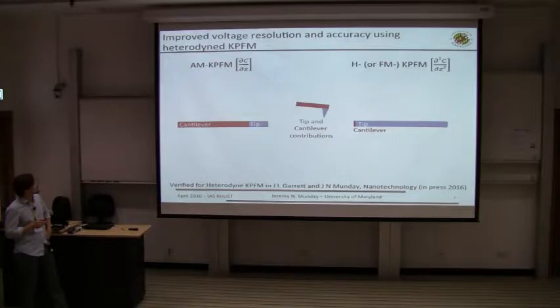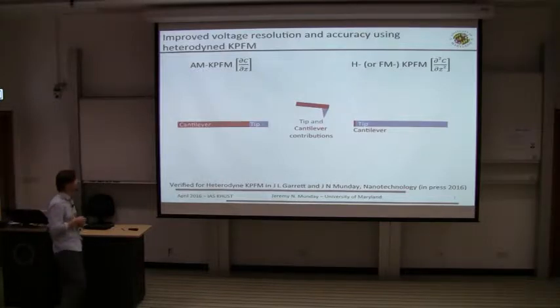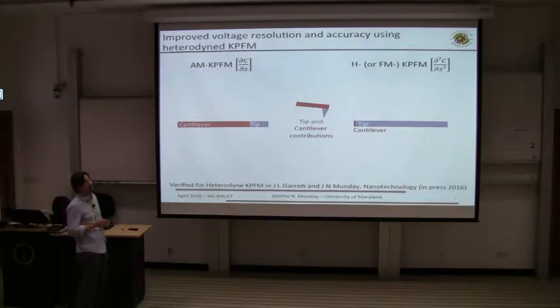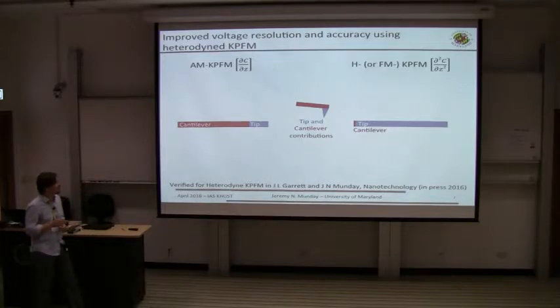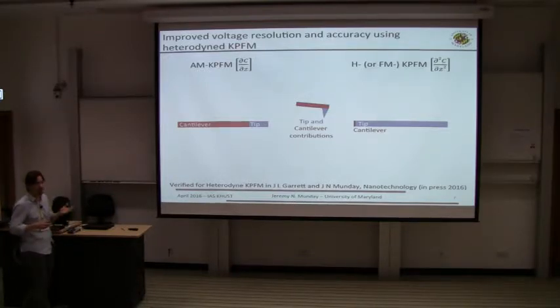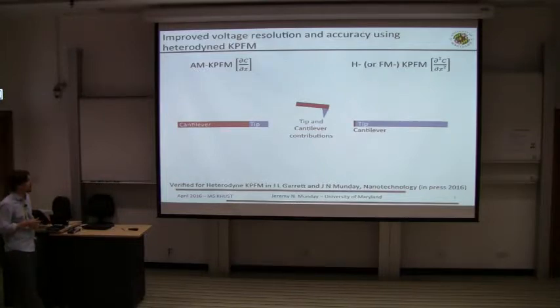Now, with the amplitude modulated, because it goes with the derivative of the capacitance, the first power, you end up getting more contribution from the cantilever than you do the tip, because you've got this very large cantilever here and a relatively small, narrow tip. So if you have something that varies more quickly with distance, then the closest interaction starts to play a bigger role, and so you can have a larger interaction just between the tip and the sample. So kind of qualitatively, you can think about it this way.